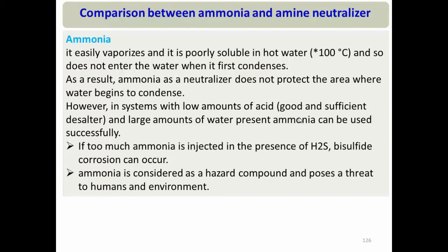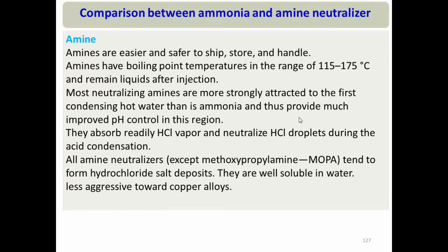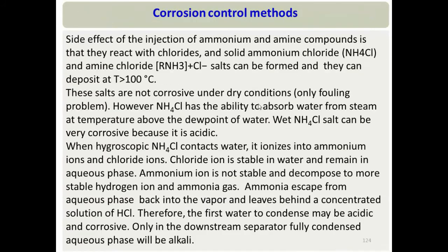Amine is a better neutralizer than ammonia. Amines are easier and safer to store and handle. Most importantly, amine solubility in hot water at the initial water dew point is much higher than ammonia, providing much improved pH control. Additionally, ammonia causes stress corrosion cracking in brass, while amines are generally less aggressive toward copper alloys. Based on these factors, amine is considered the better neutralizer.